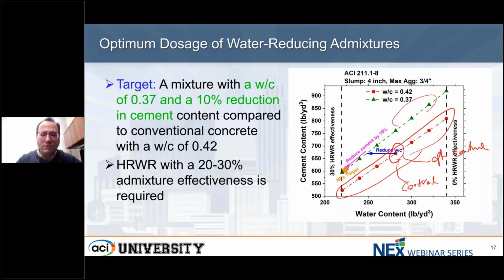So first, we're going to reduce the water cement ratio by 5%. That's what you are seeing with this blue arrow here, by 5%. So the difference here, we can move this direction. Basically, we can increase the cement content, but here we don't want to increase the cement content or reduce it by 10%. We want to keep the cement content the same, so that's why we are moving in this direction and reducing the water cement ratio to 0.37 while keeping the cement content exactly the same. So then we're going to have another mix design at this point. We're going to call that the low water cement ratio mix design, or mix design with 0.37 water cement ratio.